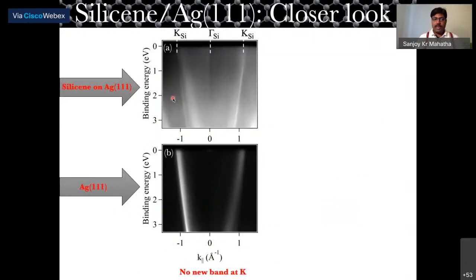So here you can see this is silver 111 and this is after putting silicene. We could see the same silver band crossing the Fermi level, and it is not related to any silicene band structure. So basically there is no new band at the K point of silicene. So the claim they made in the PRL is kind of wrong.